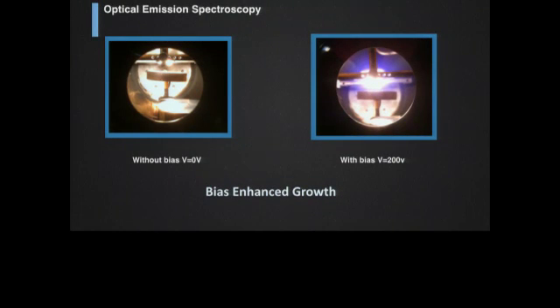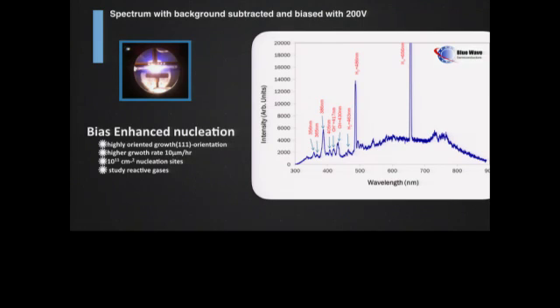We can also add a bias. This is with zero volt difference between the filaments and the stage. This is with 200 volts difference, and you can see that you've ignited a plasma, and we can actually use that plasma to study some of the gas dynamics that are going on. Also, the bias actually enhances the nucleation. You get highly oriented growth in the 1-1-1 direction. The growth rate can go as high as 10 microns an hour, and it produces somewhere around 10 to the 11th per square centimeter nucleation sites.